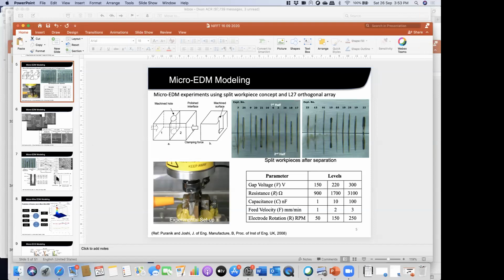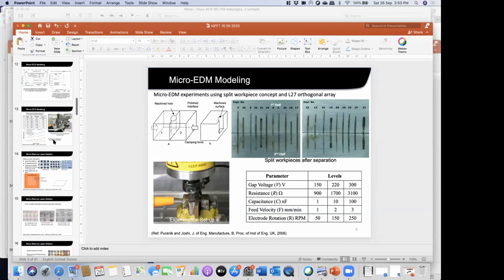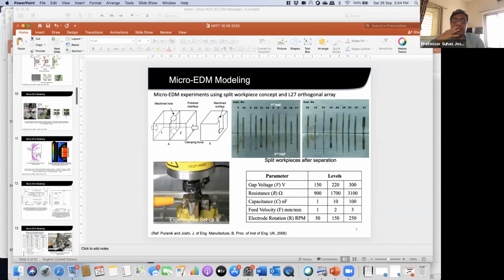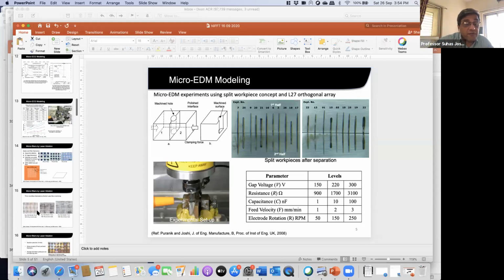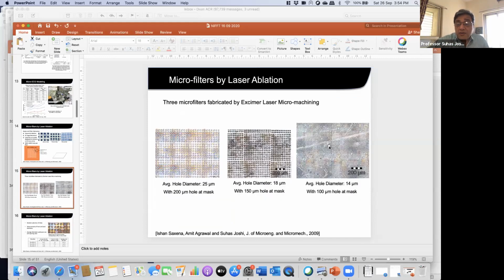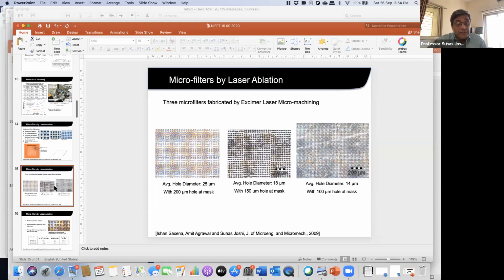And actually, with the textured surfaces, the finish was not talked about. So in the textured surfaces, the finish is not important. Finish is not required. We want some kind of textures which will do some kind of function. So these are functional surfaces where the finish is not required, but it is the size of those features. Say, for example, here the hole sizes are 14, 18, or 25 micrometer each, in that 3 to 4 millimeter size microfilter which is there.